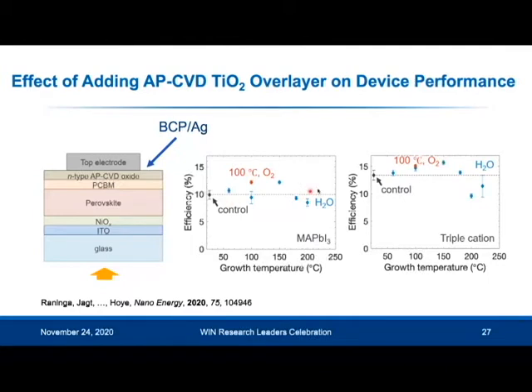And now we fixed the oxidant to water vapor, and we varied the deposition temperature over a wide range up to 220 degrees Celsius. And when we looked at the XRD patterns, we found that there was no bulk degradation even at this high temperature, because the deposition time was so short. And we can see that in the devices, we can go up to 180 degrees Celsius in the deposition temperature before we start having device efficiencies that go below that of the control.